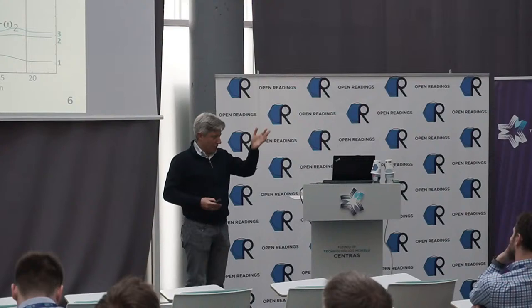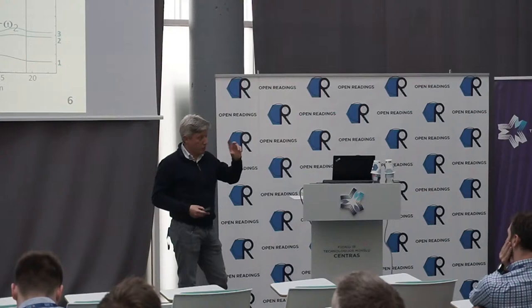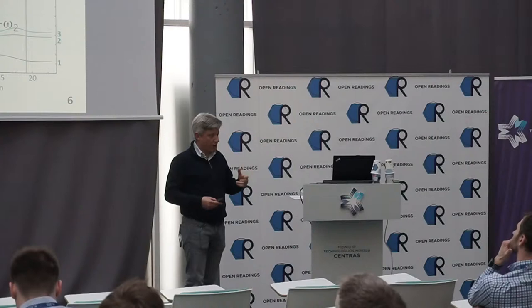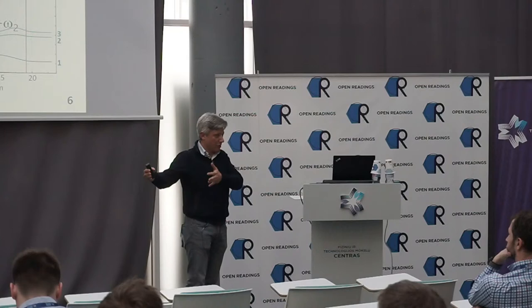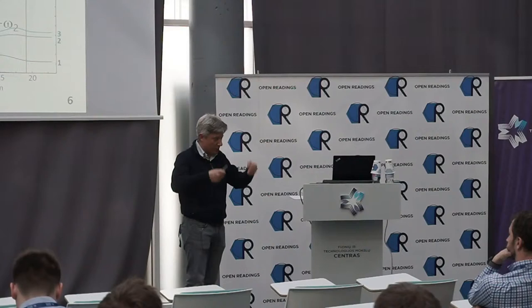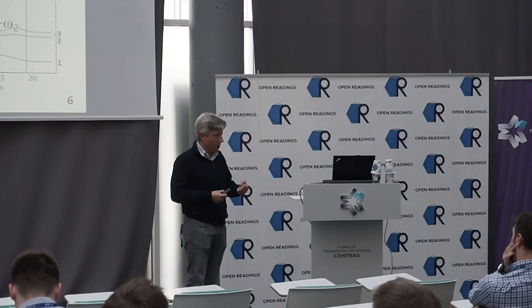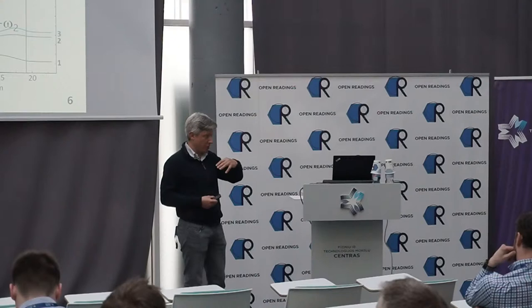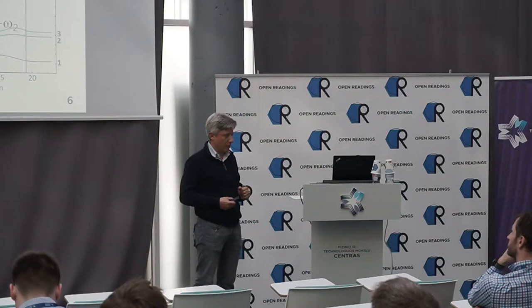Drops pretty fast. Now, our metasurfaces generate light using polarization response, the P term in Maxwell's equations. And there, just like going from electronics to photonics, we know that we are not limited by the resistance capacitance because we generate polarization from within the material itself. And so our structures are expected to have the highest performance at high terahertz frequencies. So I think this metasurface approach is very complementary to the photomixers approach.